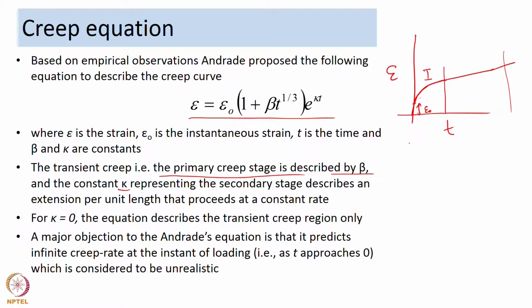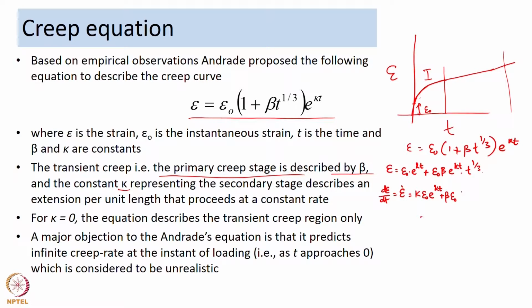So, the way to look at it is, if you write epsilon equals epsilon naught times (1 plus beta t to the power 1 by 3) times e to the power kappa t, epsilon can be written as epsilon naught e to the power kappa t plus epsilon naught beta e to the power kappa t into t to the power 1 by 3. So, d epsilon by dt, which is equal to epsilon dot, then becomes kappa epsilon naught e to the power kappa t plus beta epsilon naught kappa t to the power 1 by 3 into e to the power kappa t plus 1 by 3 e to the power kappa t into t to the power minus 2 by 3.